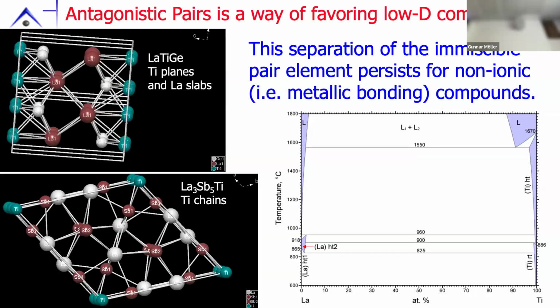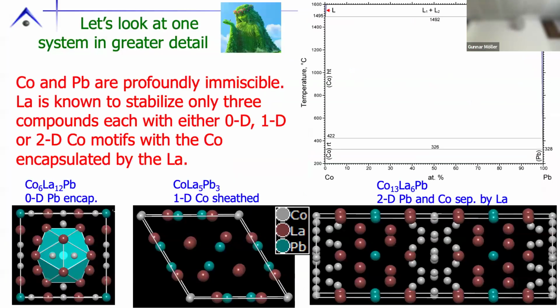And what's remarkable to me is the fact that they don't want to mix in the liquid translates into the solid of them not wanting to be next to each other. Okay, so we could look at another example. Here's the cobalt-lead binary phase diagram, highly immiscible. And by the way, most of these phase diagrams don't have any reported ternary compounds. These are just the ones I could find a few of.